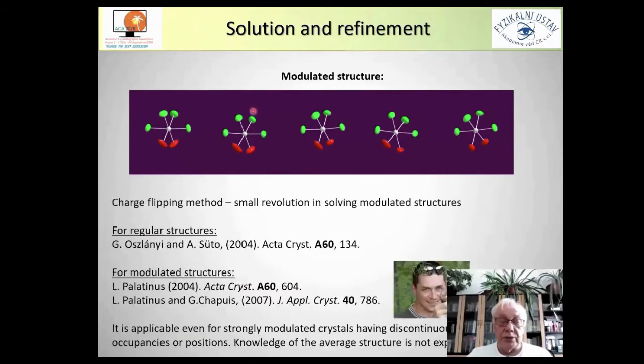Nowadays, we can take advantage of the charge flipping method, which made a small revolution in solving of modulated structures. For regular structures, this algorithm was developed by Gábor Oszlányi in Hungary, and for modulated structures by Lukáš Palatinus, and finally, in collaboration with Gervais Chapuis, the program Superflip was finished and used for solution of structures. It is applicable even to strongly modulated crystals having discontinuous modulation, so it's a very general program. In most cases, the starting model is good enough to start refinement of a modulated structure. So it's really a revolution in solving of modulated structures.